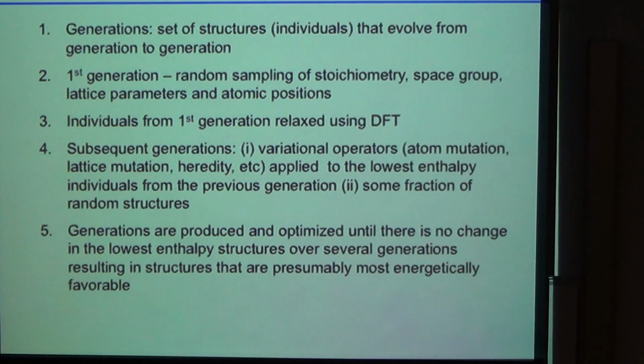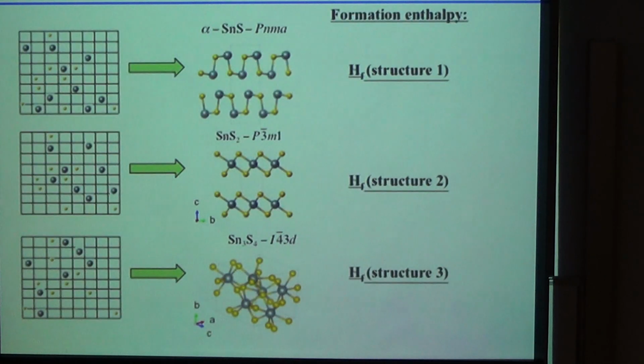We take the lowest part of the generation after we relax these, and we start applying different variation operators. Basically, we splice several structures that were close in energy and start mixing them together. Then we add some fraction of random structures. Then we create the second generation, relax, and apply these variation operators again, until we get something that stabilizes. I'm going to show you how it works in practice.